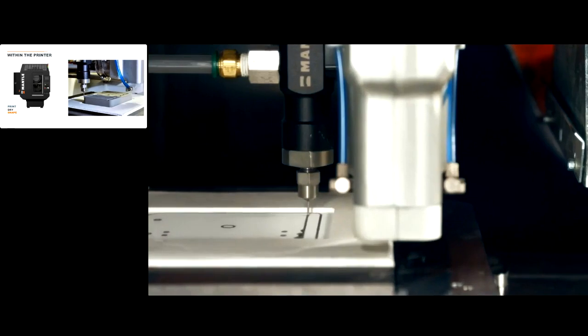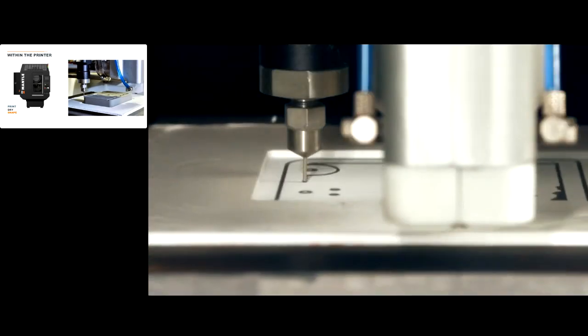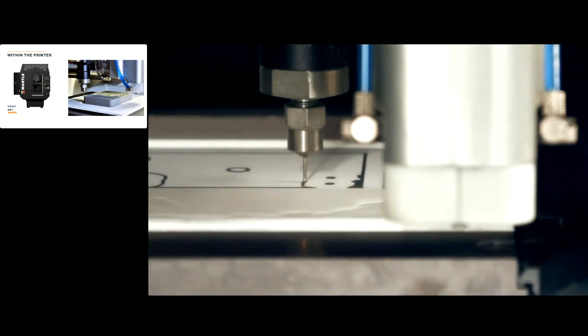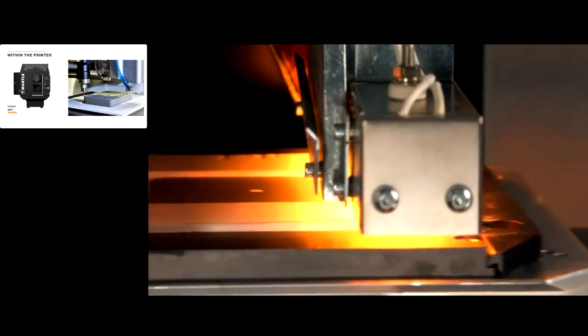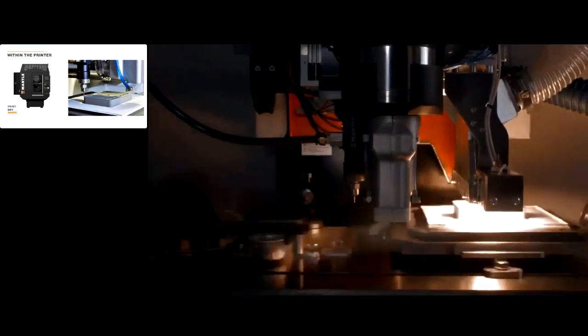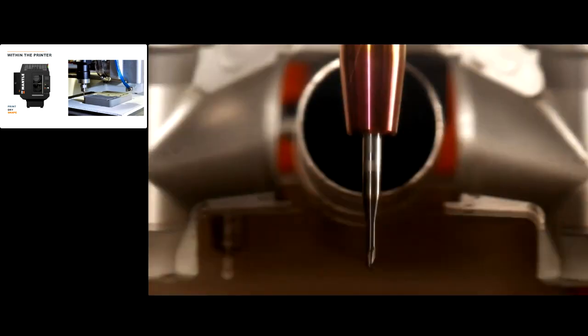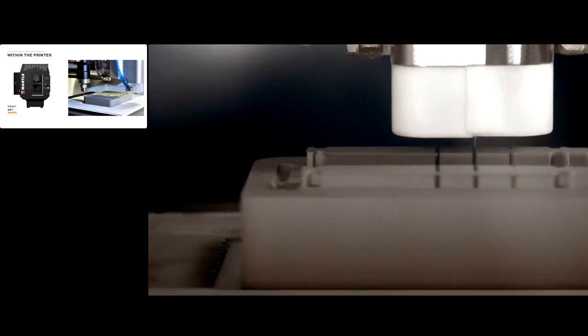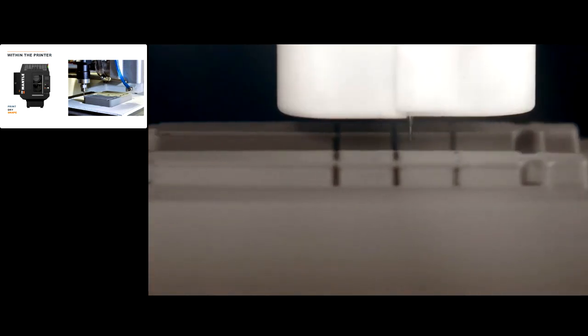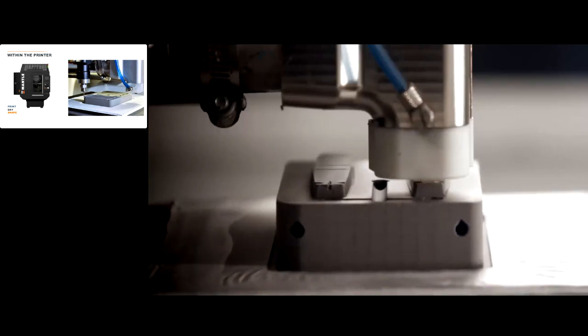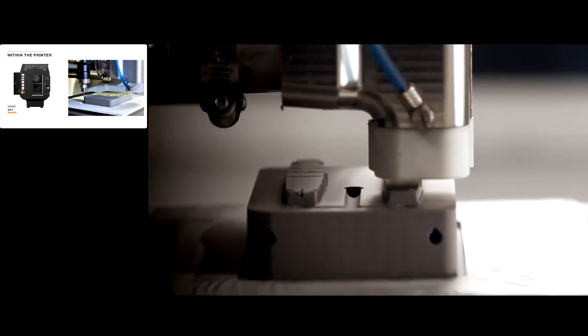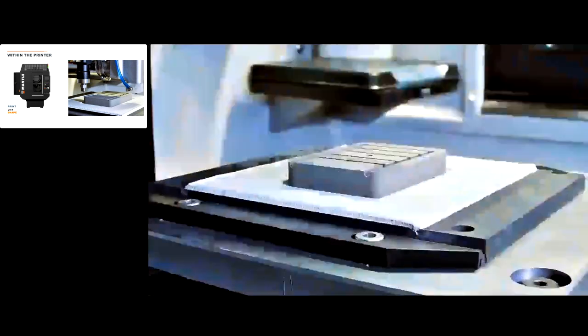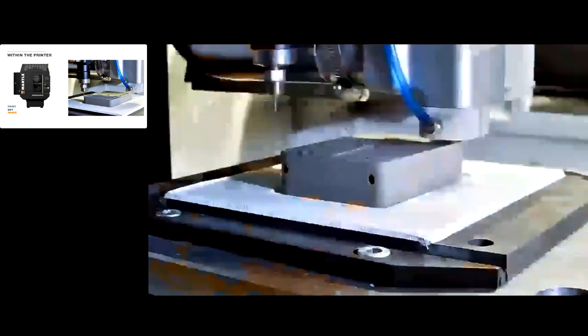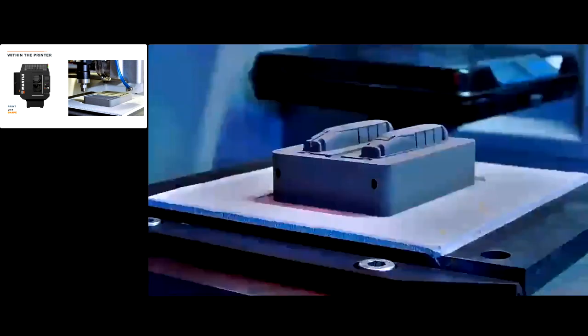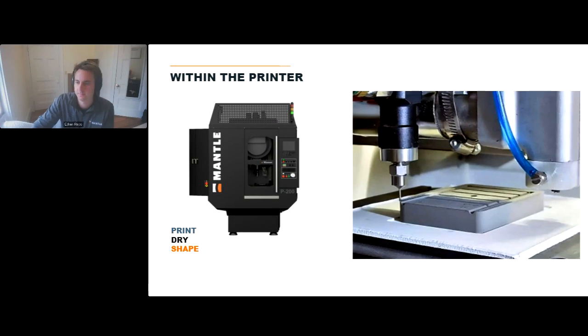I know it takes a second to pop up here, but you can see that extrusion of the paste here. Just extruding it out relatively quickly, coming through and drying that with some heat just to remove that solvent. And then using standard CNC techniques and tools, we go through and we refine the shape, improve that surface finish, and add any feature details that weren't able to be printed. So that's happening every single layer. And of course, this repeats to build up your part. All automated. It's going to work over the weekend, work overnight, etc. You just have to set it up and let it run to get your insert complete.